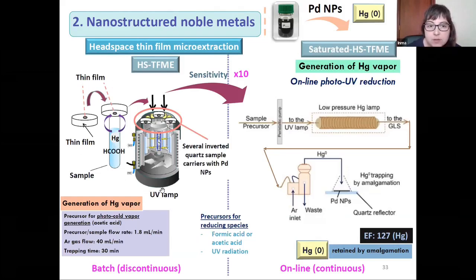First, in batch or discontinuous mode, we have the thin film of the palladium nanoparticles that we place in an inverted position over the headspace of a vial containing the sample solution or standard solution in, for example, formic acid. And then we put this vial with this sample carrier into an ultraviolet lamp to produce the generation of the mercury vapor, which is in the headspace, and then it is moved to the thin film of the palladium nanoparticles, which are then analyzed by TXRF.